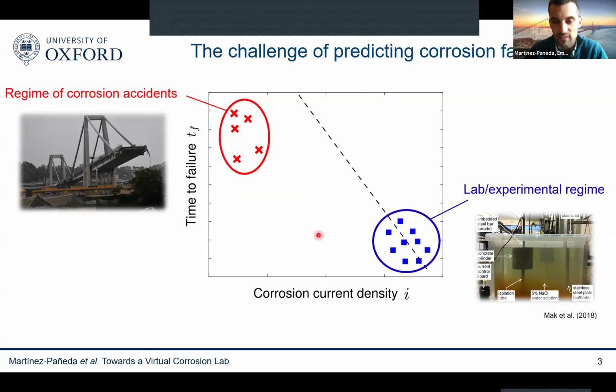This is a classic example that is illustrated here. On the y-axis, you have something like time to failure. And on the x-axis is a measure of the severity of the environment. It could be the corrosion current density, for example. And this is typical, for example, of accelerated experiments on reinforced concrete structures. Basically, what you run is some sort of experiment where you have a very aggressive environment where you prescribe an accelerated corrosion current density, so your experiments don't last forever, and therefore you obtain data in this area here. But then what you need to do is to predict what's going to happen in this regime here, where these catastrophic failures will occur over periods of decades. And of course, we cannot run experiments over decades, so going from here to here is a challenge.